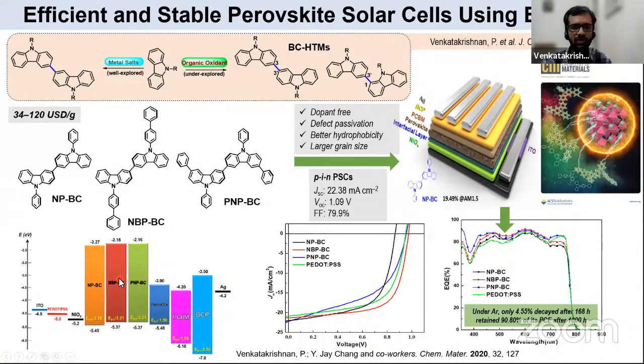Basically, these hole transporting materials are acting as a device defect passivation agent in the perovskite solar cells because these are coated on top of this. So you have the defect passivation layer. It also gives some kind of hydrophobicity to the layer, and hence hinders the moisture ingress into the perovskite layer. Besides this, it also provides a larger grain size, and hence you have uniformity and extended absorption and excellent charge transport characteristics within the device.